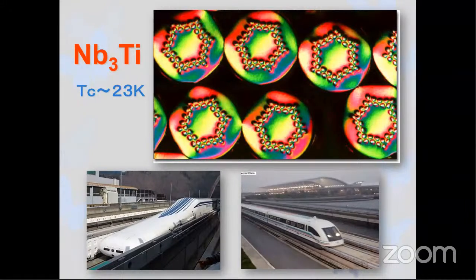So what we have to do is increase the transition temperature to a much higher temperature. The criterion is nitrogen. Liquid nitrogen is at 77 Kelvin. So if we can have a higher Tc than 77 Kelvin, we can use nitrogen as a much cheaper cryogen, making a breakthrough in the economic world.